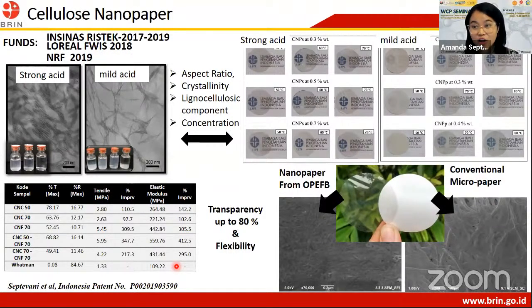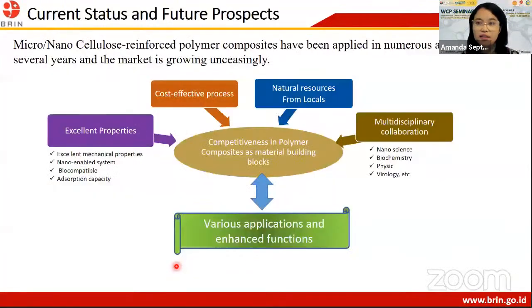In terms of transparency, we can get more transparent cellulose nanopaper if we use nanocellulose derived from strong acid hydrolysis, which usually has a rod-shaped morphology with a very low aspect ratio. While mild acid provides very tough and stronger mechanical properties. When we combine these two results, we can get both transparency as well as flexibility. So I think this is the end of my presentation.